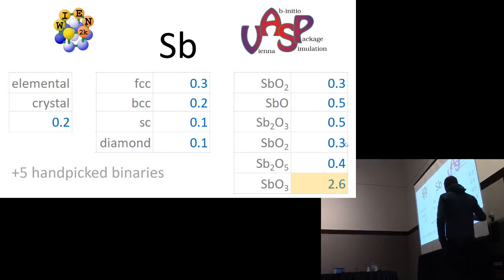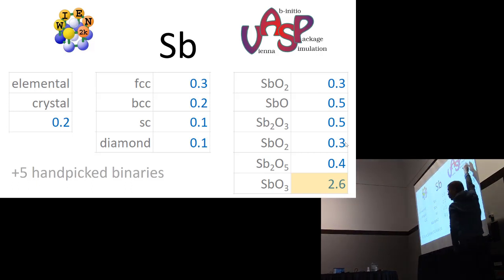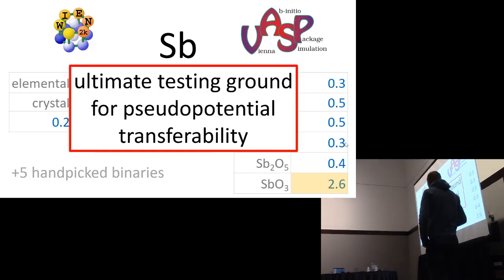These you can add to the table as well. That's not yet done in this case, but that would give you per element this kind of overview from which you could conclude: this antimony pseudopotential that was used in VASP does agree very well with all electron calculations in WIEN2K for structurally diverse and chemically diverse situations. Perhaps maybe for this high oxidation state of antimony, there is something in the pseudopotential that needs to be fixed. That's the kind of information you hope to extract from this.